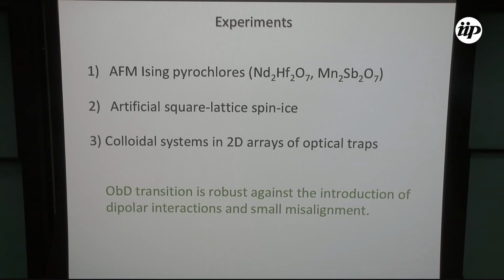And you can also think of a colloidal system. This is a proposal for someone else. I mean, we're not going to try doing these optical traps. The other thing we checked is that even in the case where you have dipolar interactions, and even in the case where it is slightly misaligned, because you know that in Monte Carlo it's very easy to say the field is pointing in this direction, when in real life it's a lot harder to do that. And we checked that within 5 degrees of misalignment, this picture should still be valid.